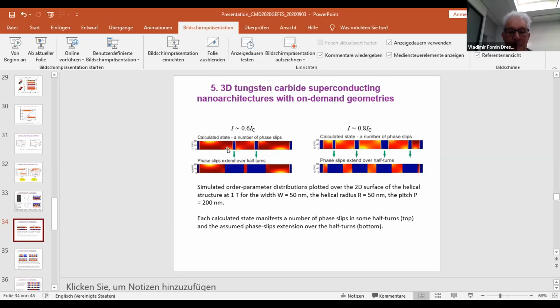The occurrence of these phase slips is obtained again on the basis of our theoretical modeling, but when in some windings the phase slips occur, even narrow, they will lead to heating, and therefore we suppose that these phase slips due to heating will spread over the respective half winding. But as you remember from one of the previous slides, these effects are inhomogeneous with respect to the number of half winding. Therefore, in some cases, the half winding remain superconducting.